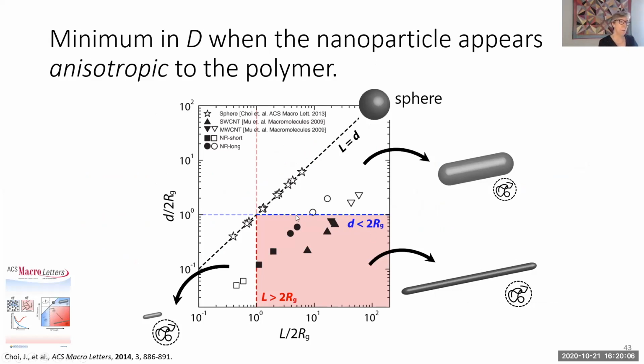And so the diffusion minimum was only observed in this red quadrant. And in this red quadrant, for nanowires, for nanorods, or for carbon nanotubes, the size of the polymer was large relative to one dimension and small relative to the other dimension. And so that minimum really has to do with whether the polymer that is moving sees that object as anisotropic. And if it didn't, like if the rod was kind of chunky or small in these two extremes, then the polymer did not identify that nanorod as being anisotropic, and the diffusion coefficient just decreased with increasing loading.